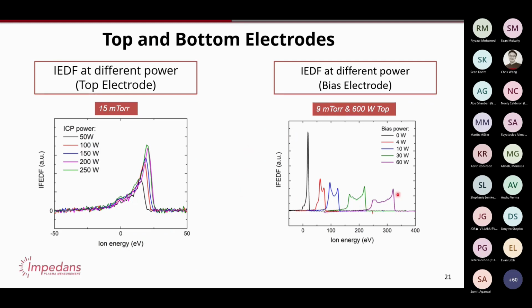Yeah, and you can go even more complicated. I can show you data examples later of using not sinusoidal waveforms but pulse waveforms. One other thing that's important here: this measurement is 60 watts. Chances are that was a generator output measurement. But your matchbox is not 100% efficient, and the matchbox efficiency depends on the plasma impedance, and on the temperature of the match. It even depends on the wafer that's in the tool, because different wafers have different capacitances, therefore taking the whole RF circuit to a different load.